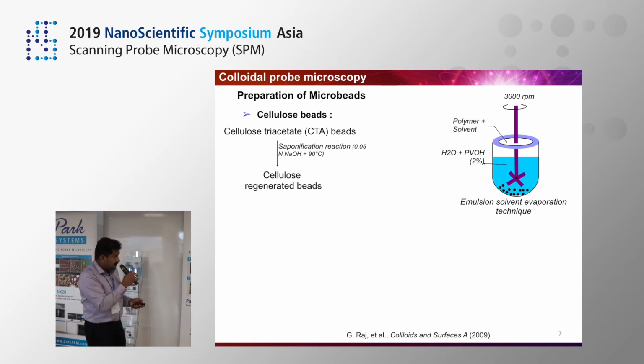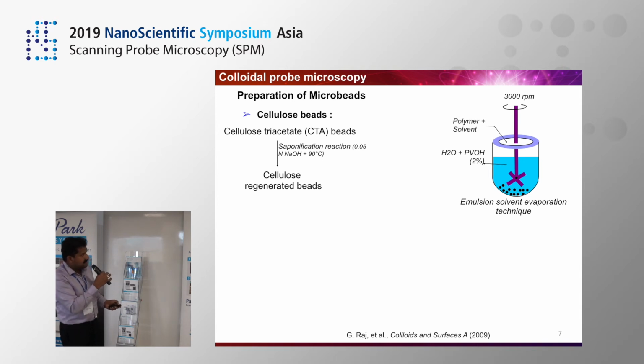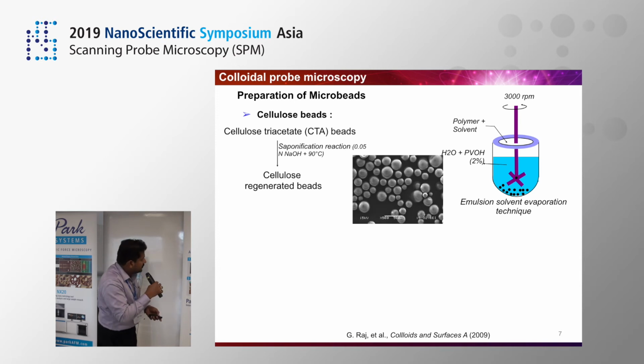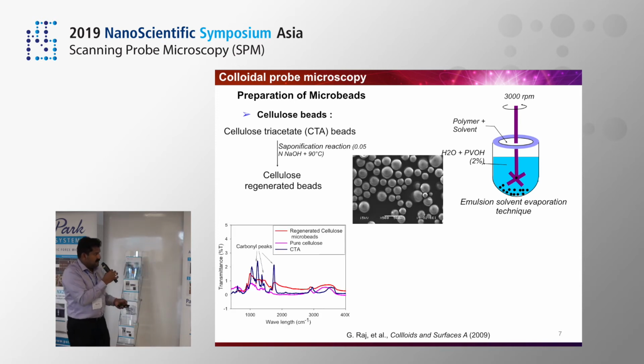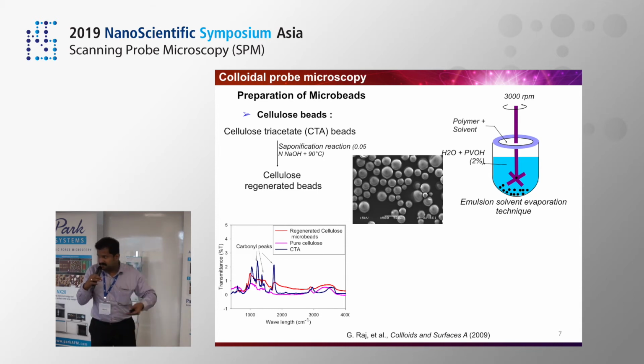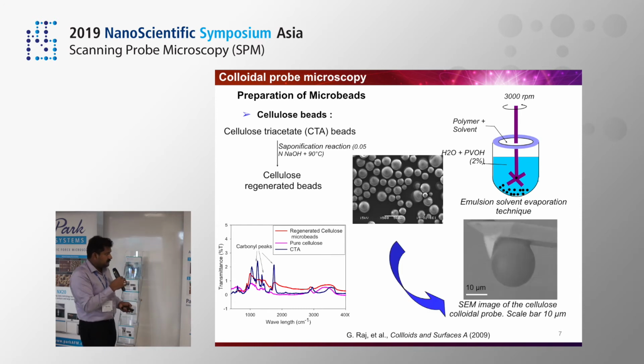This is cellulose triacetate microbeads. We take them and do a saponification reaction by treating with an alkali solution at 90 degrees, and then finally we regenerate back the cellulose, giving these cellulose beads. Here are infrared spectroscopy curves that show cellulose triacetate with these acetate carbonyl peaks, pure cellulose, the pink one, and the regenerated cellulose closely matched to the pure cellulose, indicating that the reaction was good. And once we have these cellulose microbeads, we stick one to the tip of the cantilever like that to get this colloidal AFM probe.